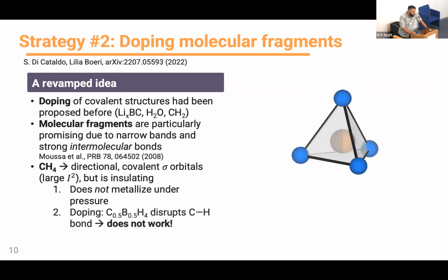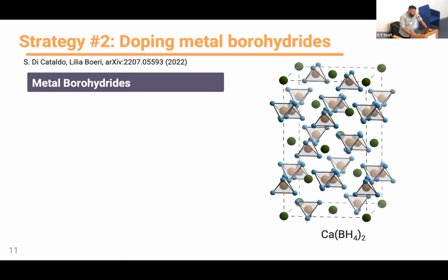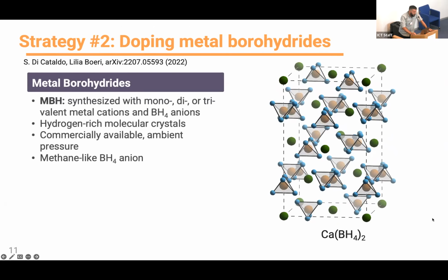And if we tried to dope it, this wouldn't work. The reason is that we are trying to dope a molecule on a site which is very strongly bonded. We cannot do that. We are disturbing our structure too much. So doping should not involve the covalent sublattice. It should happen somewhere else. This is the idea that led us to consider this family of structures that I'm showing here on the right, which are metal borohydrides.